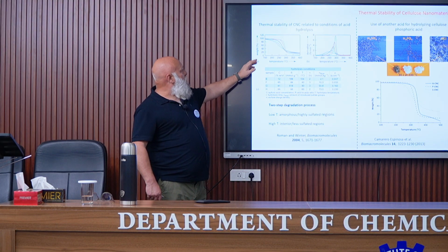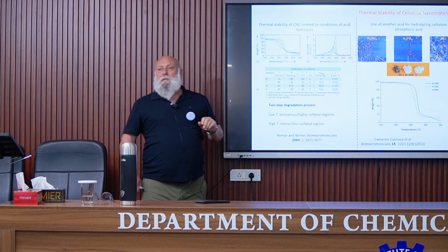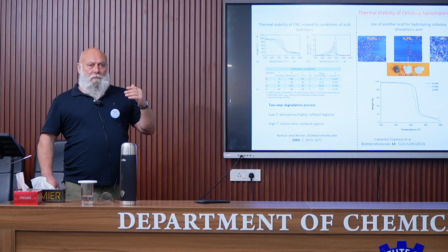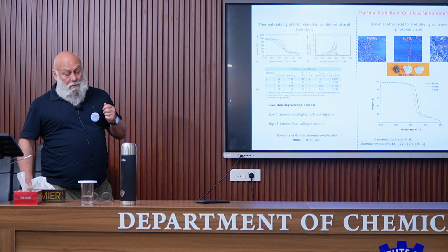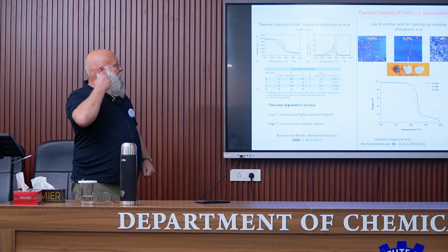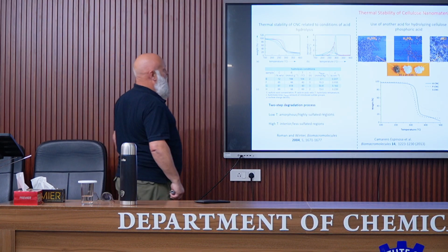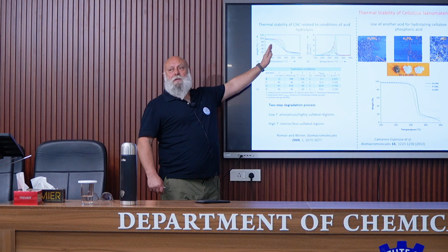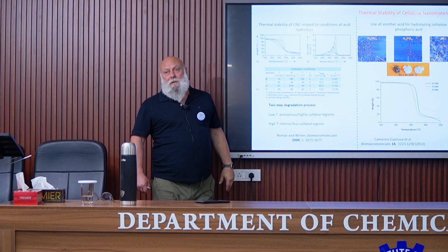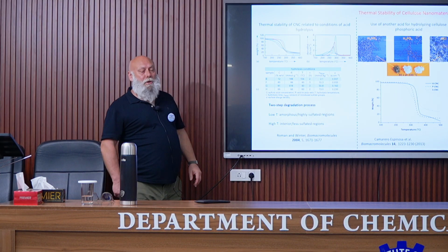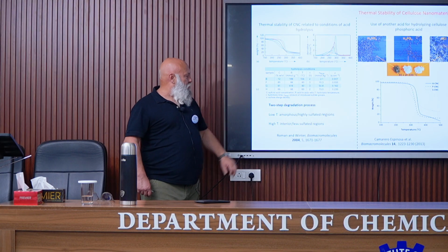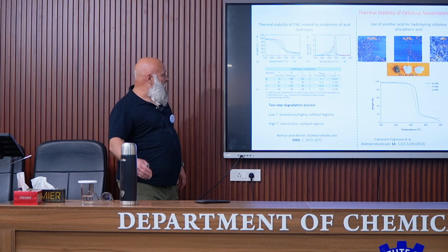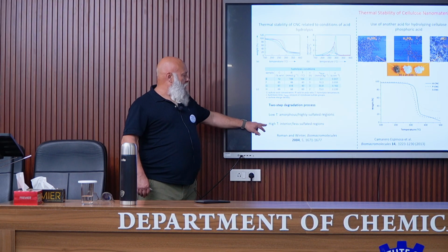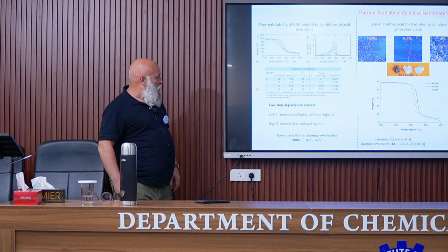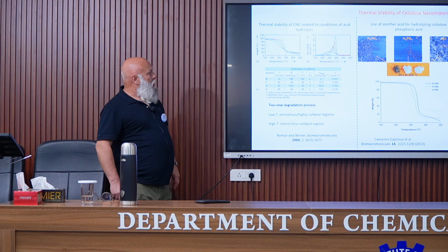TGA, thermogravimetric analysis, was performed for nanocrystals that have been extracted using sulfuric acid hydrolysis with different strengths, different concentrations. And it was shown that as the severity of the acid hydrolysis treatment increases, the thermal stability decreases. What was observed also is that it was a two-step degradation process. A low temperature process that corresponds to the degradation of amorphous or highly sulfated regions, and a high temperature process which corresponds to the interior or the less sulfated region.